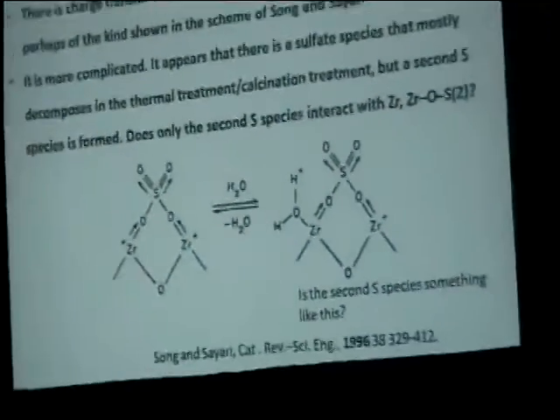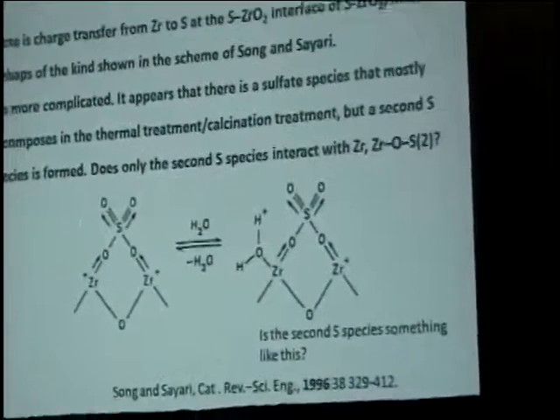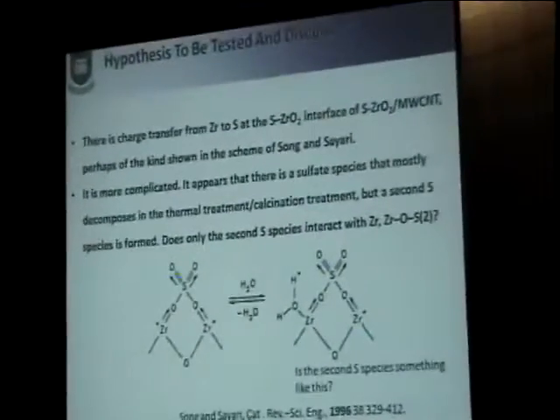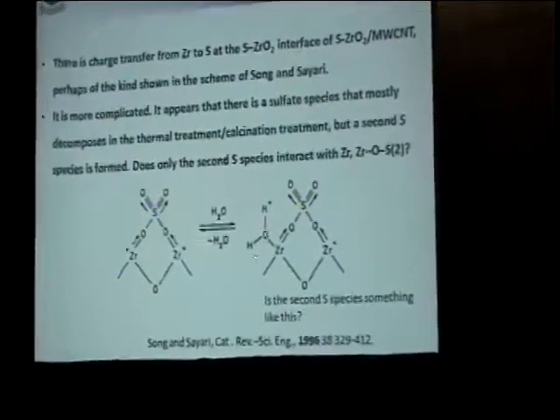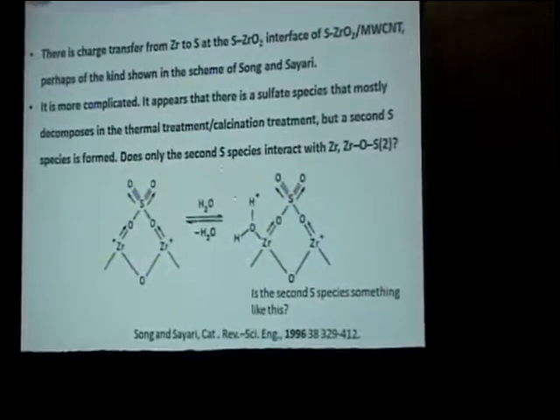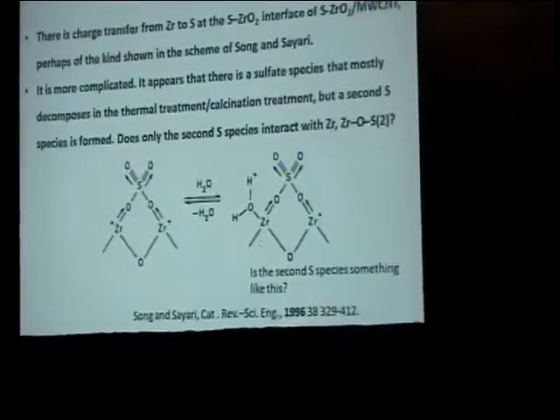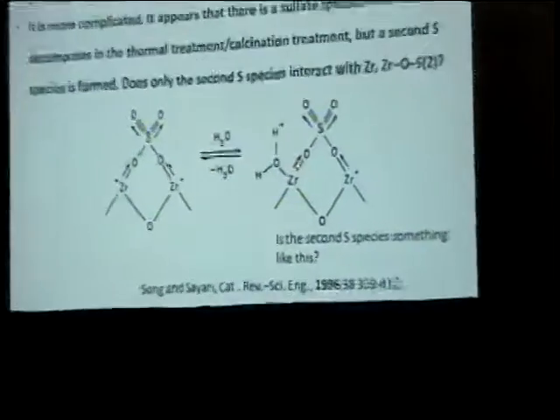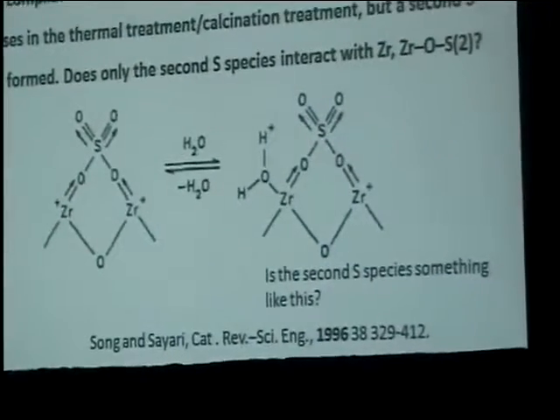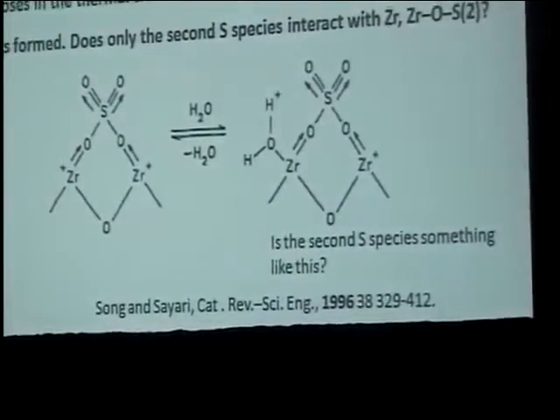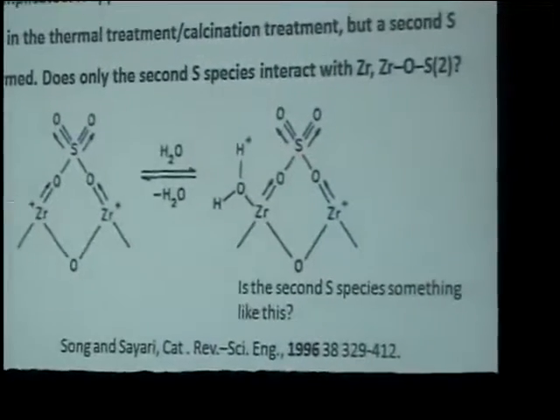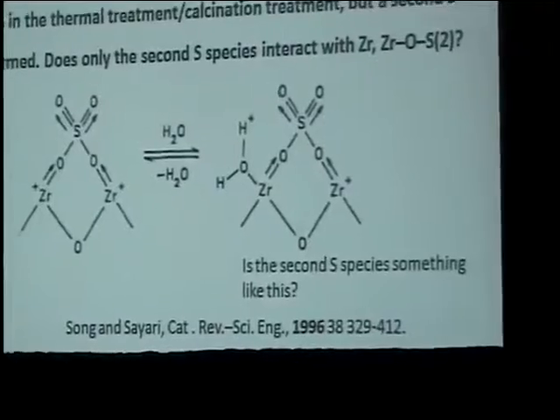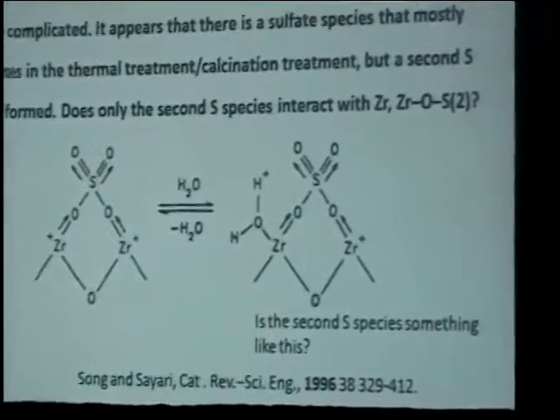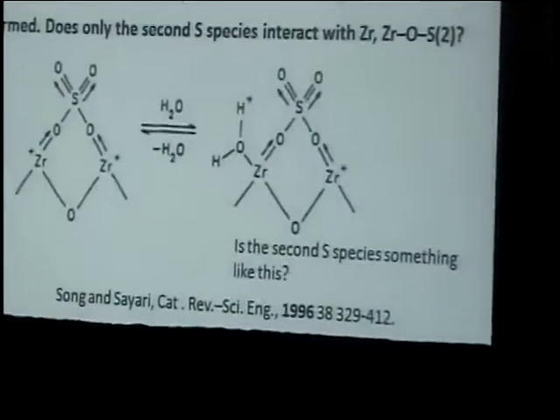Now, there are several reviews in the literature of sulfated zirconia, and there are, I don't know the exact number, perhaps as many as 30 pictures of what the sulfated zirconia sites might look like. Here's one of them. And one of the things that I want to talk about is the charge transfer that we can see as we look at the zirconium edge or the oxygen edge and the sulfur edge. And with respect to the sulfur edge, I'll try to convince you that there really are two species, a sulfate species, and then whatever the second species is that is actually the catalyst. And so what is that, and how does it share electrons? I guess it's a subtitle for me.